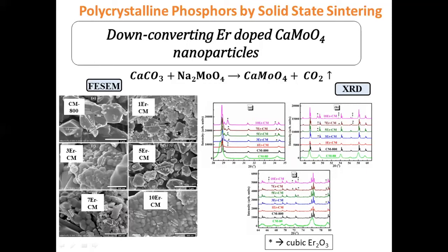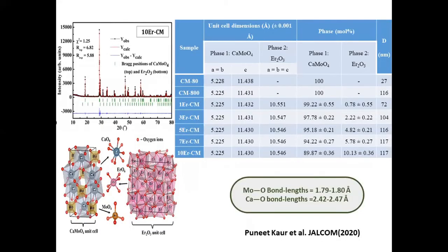Calcium molybdate has a tetragonal crystal structure. So we did synchrotron X-ray diffraction, very high resolution powder X-ray diffraction studies at the Raja Ramanna Center for Advanced Technology. These are some of the XRD patterns. So the counts are very high and the resolution of the instrument is very high. So you can do very accurate Rietveld analysis. When you do Rietveld analysis, you can find the structure of a material. You can find what is the space group to which it belongs, whether it is tetragonal. And of course, calcium tungstate and calcium molybdate, they are both tetragonal unit cells.